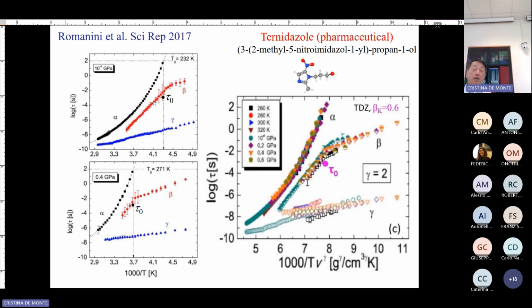So in an old experiment like this case, done in Tamarit's group in Barcelona by Romanini, they look at the alpha, look at the tau, look at the beta. Before you, this is the 10 to minus 4 gigapascal, basically room pressure, and they find this alpha and tau 0. I mean, so JG, and when they test the coupling model, is right there. So this tau 0 is the same thing. It always works. That's why. And also this gamma is nonsense. We don't need to worry about it. It's a very local motion.